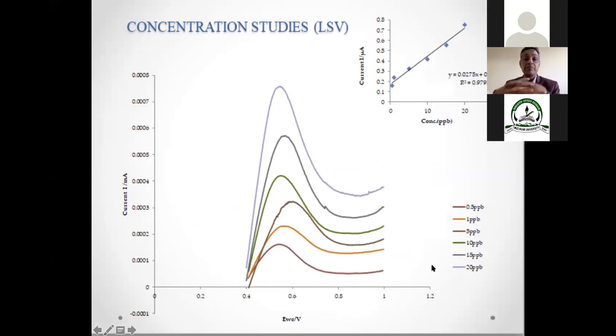So concentration dependence studies were further conducted. Here you can see that with increasing concentration, the peak height increases. This is the stripping data, LSV, that we obtained. We try to see how the current is affected by the concentration. When you increase the concentration, the current increases linearly, and we have increased the concentration from 0.3 ppb up to 20 ppb.